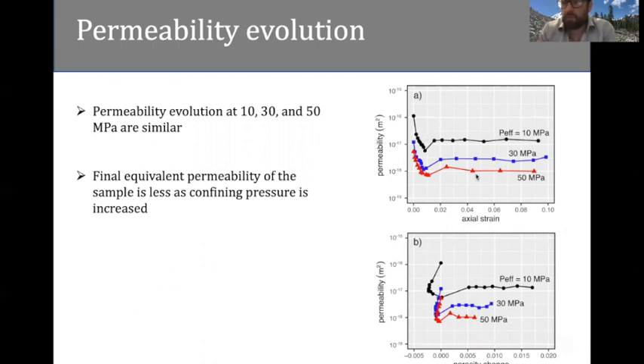So these summary diagrams show what I've been describing in the previous slides, in that the permeability evolution for the three experiments is qualitatively very similar. We see a decrease, an increase due to macroscopic shear fracture formation, followed by a more or less constant permeability during the frictional sliding on the fault surface. Qualitatively, they're very similar. Quantitatively, the permeability of the sample at the end of the experiment is higher when the effective pressure or depth is lower.